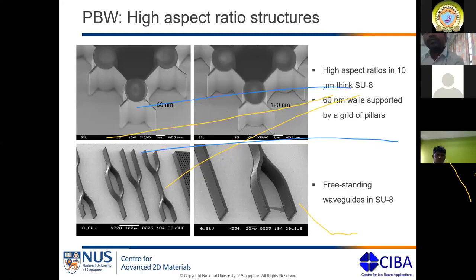The problem with this kind of structure creation is that these are very high aspect ratio structures. You can see the wall height is about 10 micron, and you can never go into a material that deep with electron beams, right? So you have to use something else, and since a proton beam doesn't spread much inside the material, you can use proton beams to create this kind of structure. This is a good example of creating structures of high aspect ratio, which were missing earlier. You can see there are other structures which you can create in SIBA. So this is particularly confined within the lithography part.